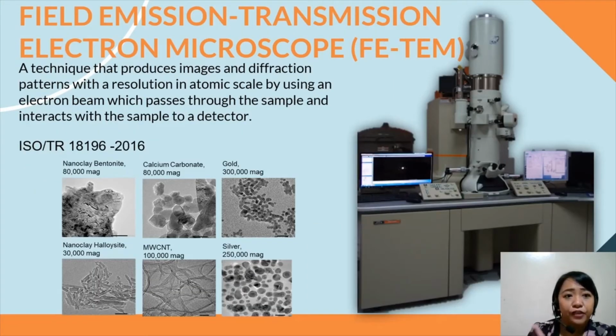Next, we have the field emission transmission electron microscope, or FETEM. It's a technique that produces images and diffraction patterns with resolution at the atomic scale by using an electron beam which passes through the sample and interacts with the sample to a detector. So with our system, we can get the morphology, determine the crystallography of your material, and perform elemental analysis as well.